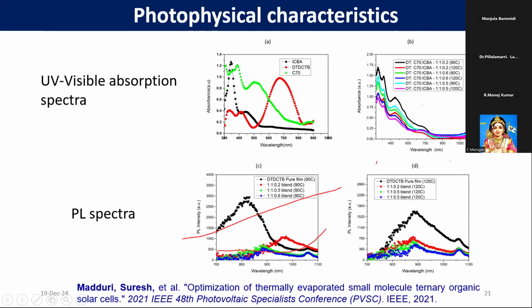We also tried to do the photophysical characterization, like absorption of the individual films and blend films, and we also tried to calculate the photoluminescence spectra. Luminescence spectra is nothing but emission spectra, showing with respect to the donor how the blend films behave and what the recombination dynamics are. So this is the donor and the remaining ones are ternary blend films, and the ternary blend films are giving lower emission intensity, meaning not many recombinations are happening in comparison with the pure donor film.